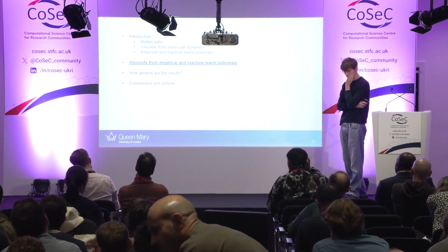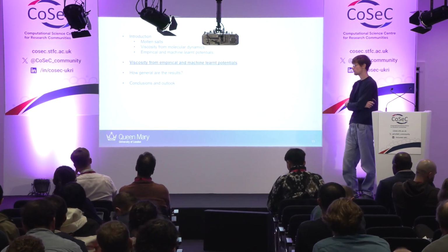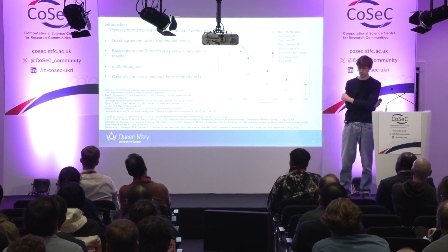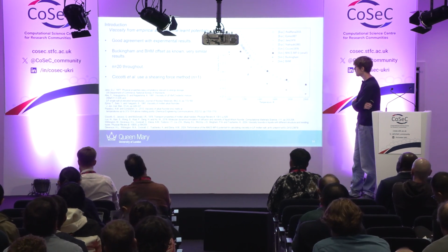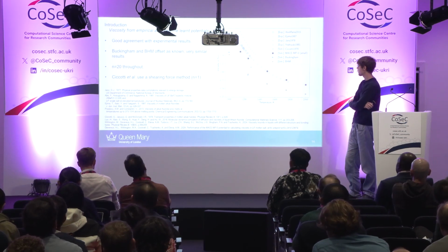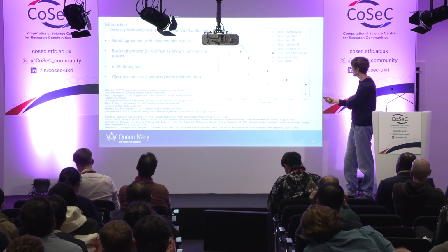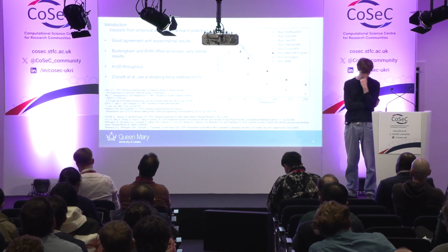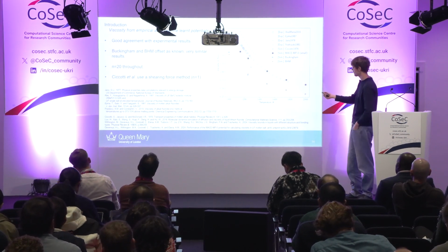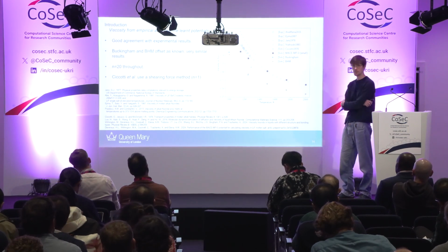So that's the introduction to the systems we're looking at and the methodology we're using, including the various potentials. Moving on to the results we can obtain. This is looking at the viscosity we can obtain via the Green-Kubo method for MACE with the black squares up here, and also the BHM and Buckingham models down below, which are known to exhibit this offsetting on the temperature axis, in other words an underprediction of the experimental data, which are the unfilled circles.